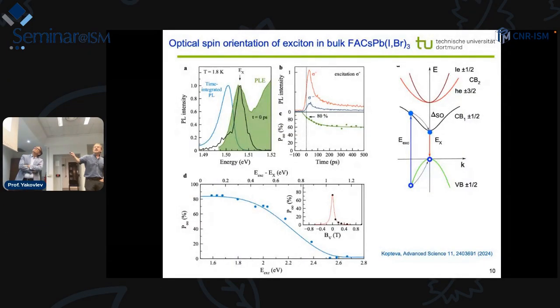In gallium arsenide, the conduction band will be just the spin state with orbital momentum 0. In perovskites, in fact, it comes from the Γ6 state, spin 1/2, and then this is the spin-orbit state. A pure contribution of the angular momentum.